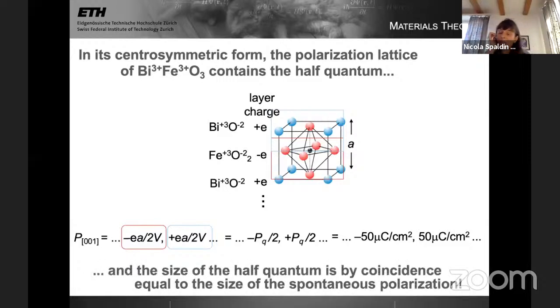And if you remember back to when we first discussed the polarization, the spontaneous polarization of bismuth ferrite, the magnitude in the 001 direction is also 50 microcoulombs per square centimeter. This is totally coincidence. It's just a consequence of how much the bismuth atom happens to displace. But by accident, the size of the half quantum, the size of the polarization in non-polar bismuth ferrite, is equal to the size of the spontaneous polarization.